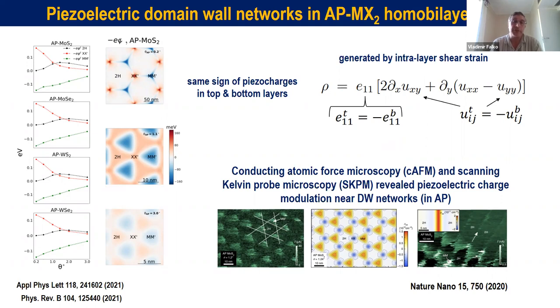And this basically starts modulating the position of the band edges in the same way for the conduction and valence band. As a result, the corners of the domain wall network, where this effect is the largest, start becoming the minima and maxima of the potential, producing kind of quantum dots which separate geographically on the Moiré pattern the minima of energy for electrons and holes. So those we can identify, and the charges that correspond to this have been measured by scanning Kelvin probe microscopy, and they reasonably correspond to what we calculated, knowing the piezoelectric parameters of the crystals.